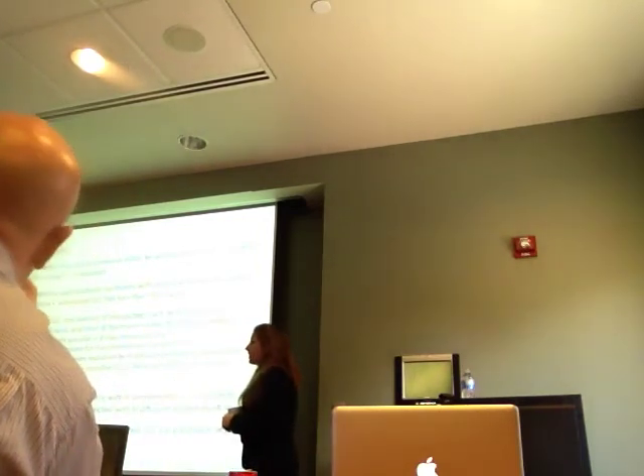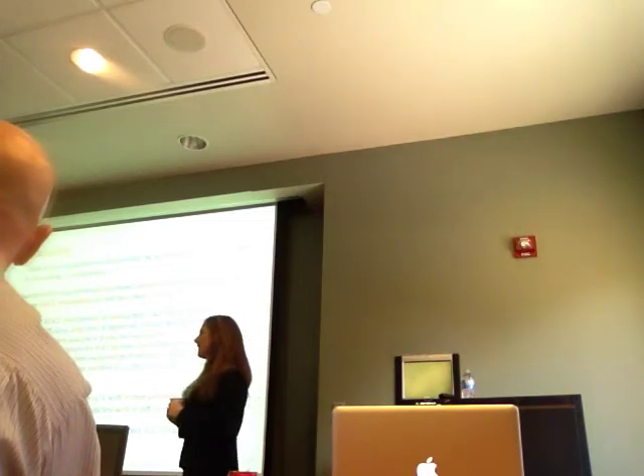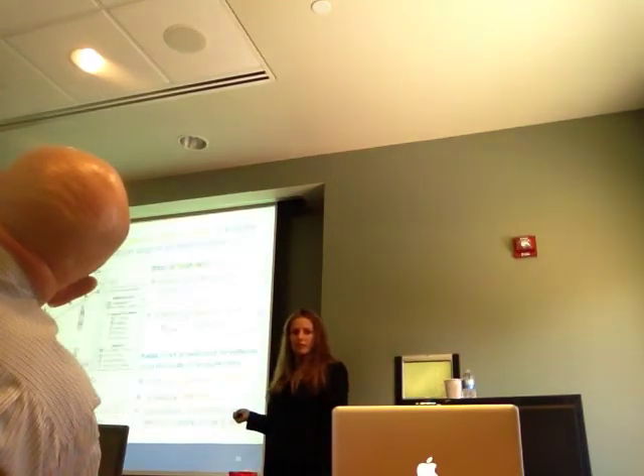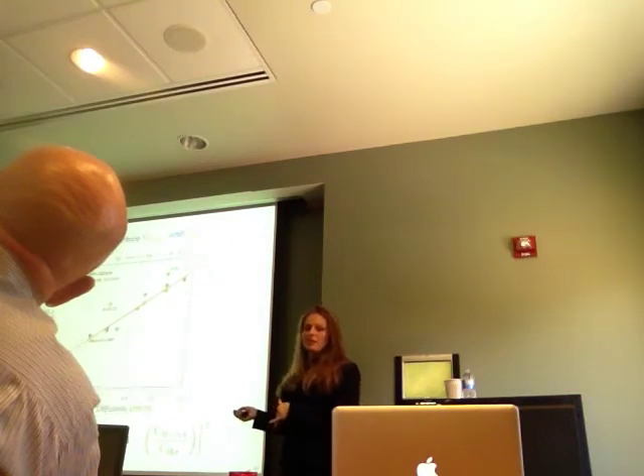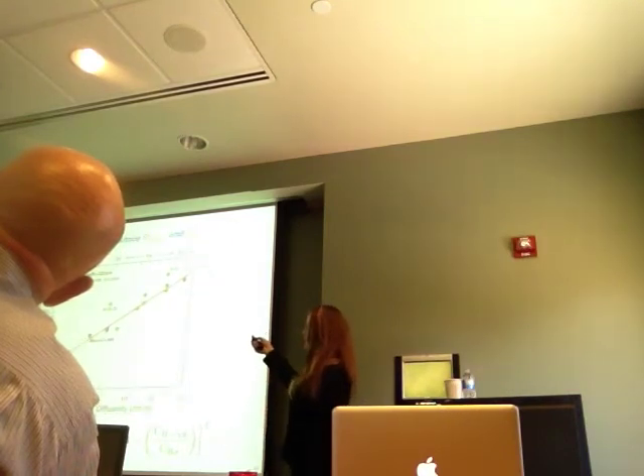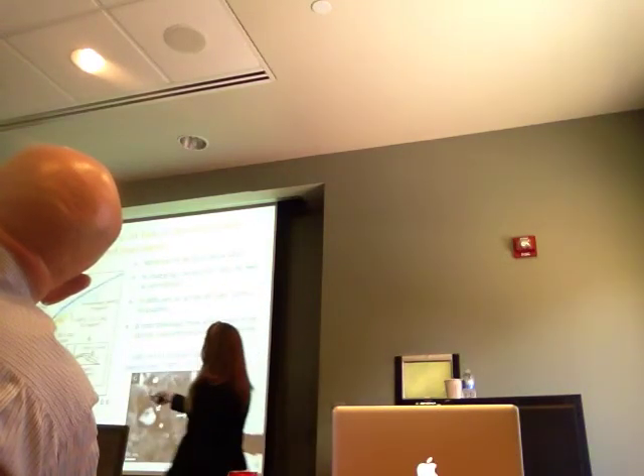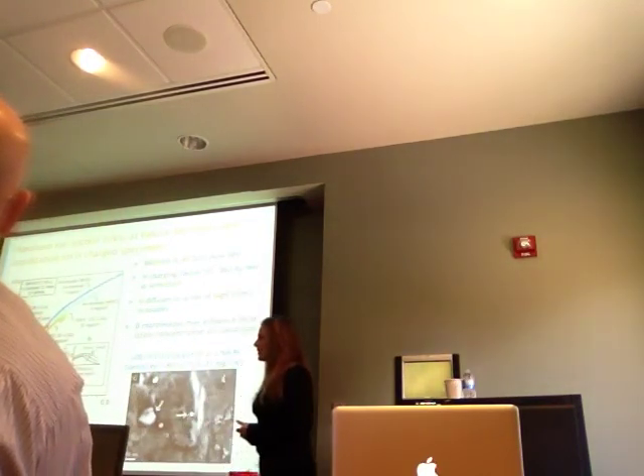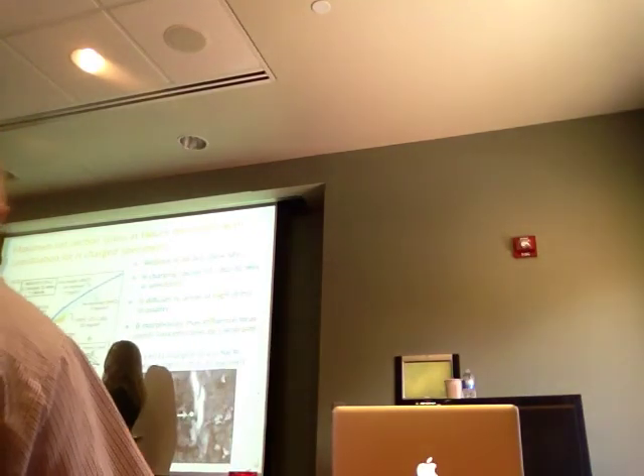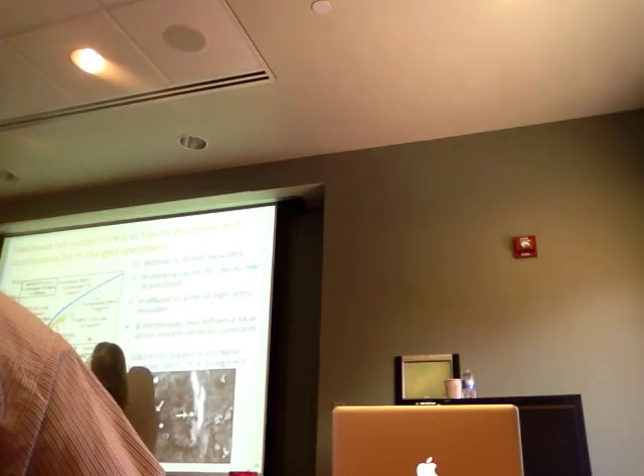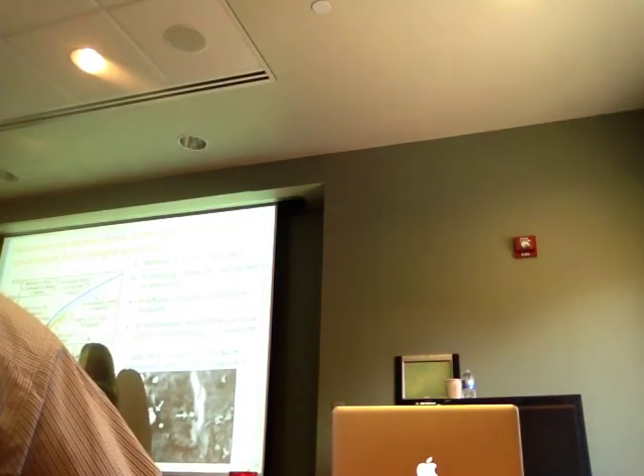Is there any real physical meaning of the X crit, or is it just a fitting number? Yeah, X crit is usually the maximum stress ahead of the crack tip. So, I have a drawing on that slide. It's usually what it's attributed to. In this model, since it fit the data, we put it here. But in fracture mechanics, you'll have a nice stress gradient in your crack tip that's controlled by your stress level, your microstructure. A lot of different things go into the X crit. But this could be one of the main reasons that you have that high stress there. So you're going to have maximum stress at this point. So once you put hydrogen in there, your grain boundaries will break.